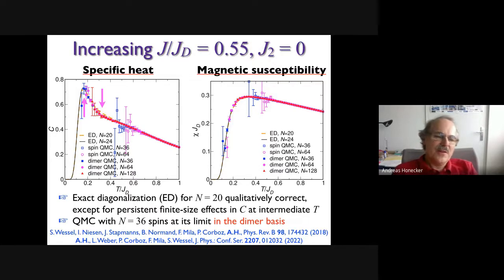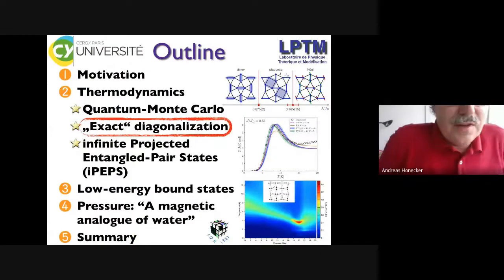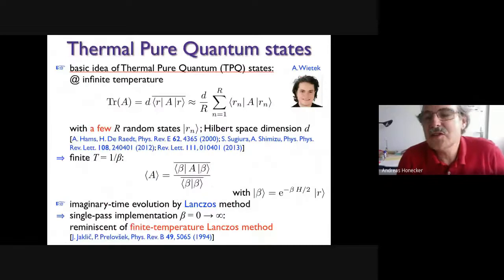But with respect to the data for this larger ratio, you can also see that the differences with respect to ED, in particular in the specific heat, get bigger as you crank up this exchange ratio. Well, that is about the limit that we can go with quantum Monte Carlo. Strontium copper borate is a bit further, so unfortunately, by that method, we can't get to strontium copper borate. So we have tried two other methods. One is exact diagonalization. And since I see time running, I will go a bit quickly on that.